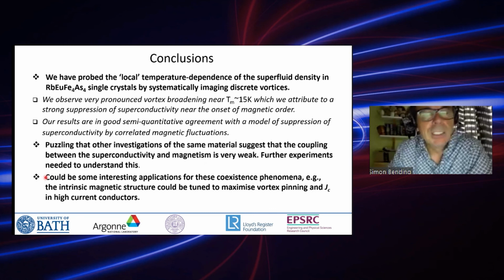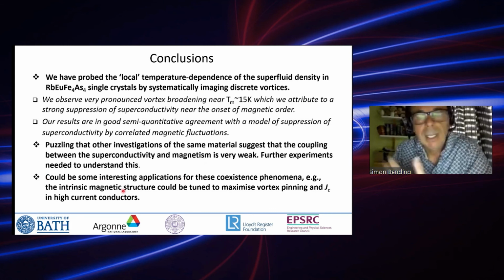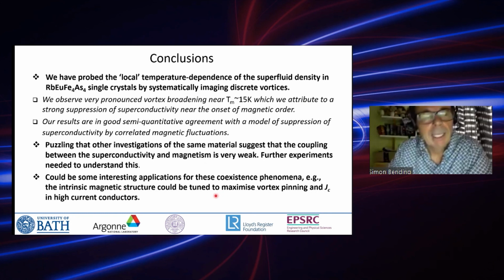And nevertheless, I think there could certainly be some interesting applications for these coexistence phenomena. For example, the intrinsic magnetic structure in certainly ferromagnetic superconductors, not necessarily these ones, but there are other truly ferromagnetic superconductors. The domain structure could be optimized to maximize vortex pinning, increase the critical current density, and produce very high field, high current conductors.